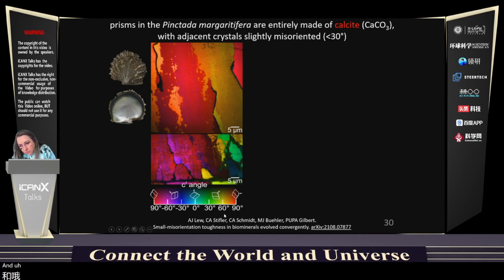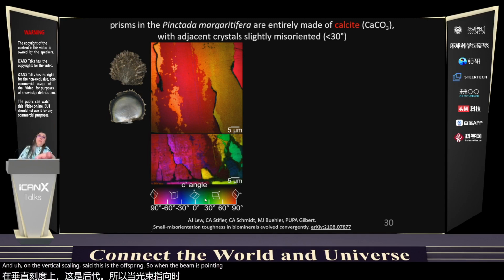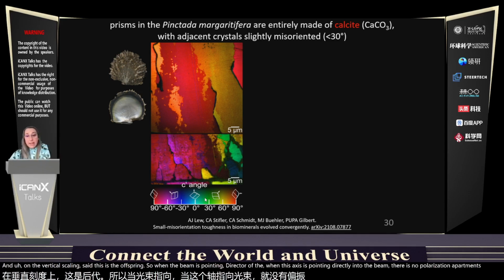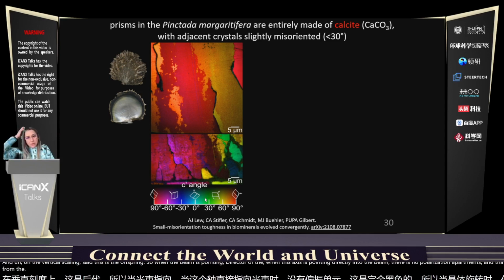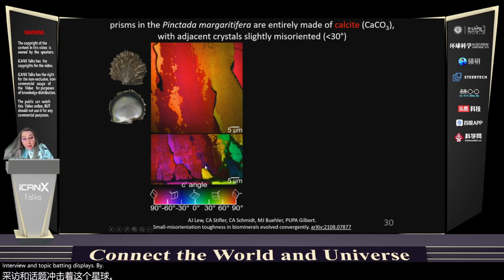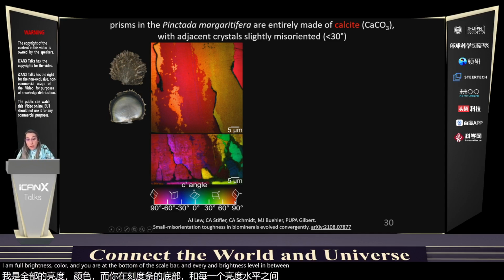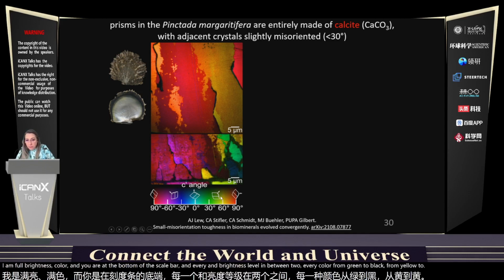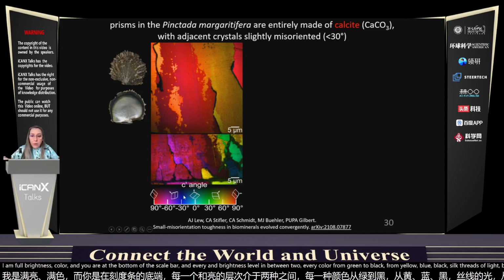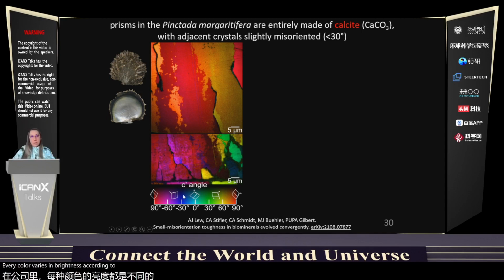And on the vertical scale instead, this is the off-plane. So when the c-axis is pointing directly into the beam, there's no polarization dependence, and that's totally black. So as the crystal rotates, absolutely nothing happens from the polarization point of view, and so PIC mapping displays black. And when it's in plane, full brightness color, and you are at the bottom of the scale bar, and every brightness level in between. So every color from green to black, from yellow to black, to red to black, blue to black, and so on. Every color varies in brightness according to this off-plane angle.